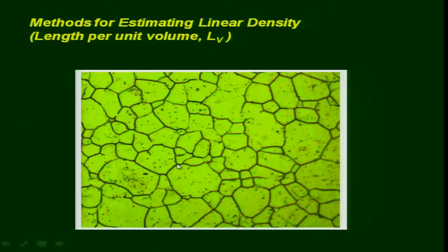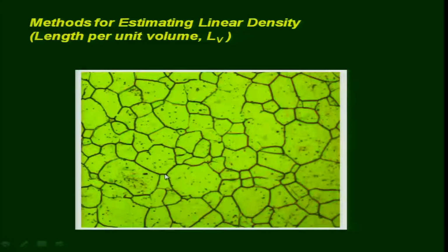In fact, the actual nucleation can take place heterogeneously on those triple edges. Therefore, we would like to know what is the total triple edge length in a unit volume. The larger this length, the more such nucleation sites are available. Similarly, the larger the grain boundary density, again more heterogeneous nucleation sites are available. All of that affects our nucleation kinetics as well as the total phase transformation kinetics.